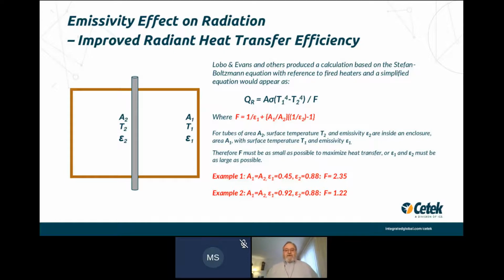So let's look at a little bit of theory and see if we can understand how the coatings actually work. You can see on the left a schematic of a refractory lined box with some tubes in. A1, T1, and E1 are the area, temperature, and emissivity of the refractory lining. And A2, T2, and E2 are the area, temperature, and emissivity of the tubes inside there. So Lobo and Evans and some others used the Stefan-Boltzmann equation as a basis for creating an equation for heat transfer from the refractory to the load inside a furnace. And they came up with that equation where QR equals the function divided by F. The function is obviously the Stefan-Boltzmann equation with T to the fourth functions inside there.